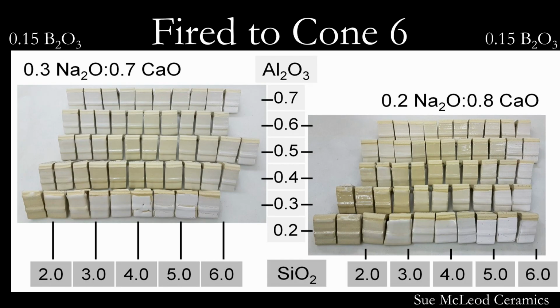For the project, I created 2 separate Stull maps where I mixed a glaze sample for each point on the map and fired them all to cone 6. Here are the tiles arranged as if they were on Stull's map. Each row represents a constant alumina level, and the silica increases from left to right. Map number 1 on the left has a flux ratio of 0.3 to 0.7, same as Stull's original map. Map number 2 on the right has a flux ratio of 0.2 to 0.8. For both maps, I used sodium as the alkali metal flux, or R2O, and calcium as the alkaline earth flux, or RO. As I said before, all tiles have a boron level of 0.15, and the clay body used was Plainsman M340.